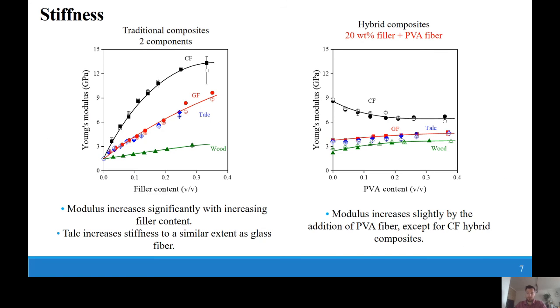So this slide shows the results of stiffness of the composites. On the left side, you can see the results of traditional composites, while on the right side, the results of the hybrid composites. Composites prepared without coupling agent are marked with empty symbols, while full symbols indicate the addition of the coupling agent. In the case of traditional composites, the stiffness increases significantly with increasing filler content. The carbon fiber increases the stiffness to the greatest extent, while talc can increase the stiffness to a similar extent as the glass fiber. So we can conclude that the extent of the reinforcement depends on the modulus of the components as well as on their volume fraction in the composite.